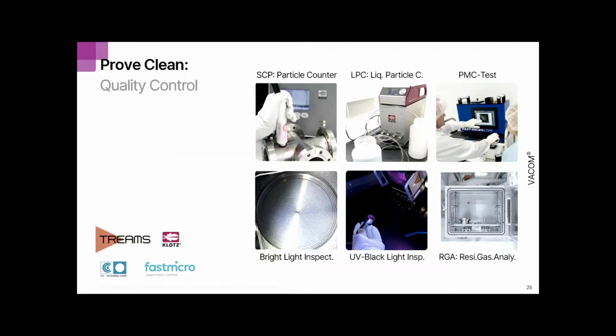So great, we've made the part clean, but you need to prove it as well. Otherwise, what are you doing? So for this, we have particle and filmic contamination specifications, for which we use different parameters and different test methods. So we have a particle counter, for example, a liquid particle counter, or a PMC test, which is a particle measurement card. For filmic contamination, you think about bright light, black light inspection, and RGA analysis. And RGA analysis is really a quantitative analysis which will actually give you information on the type of contamination that's left on your system. You can use it as a sort of troubleshooting if you're having issues with contamination of your assemblies, for example. You can use RGA to think about where that contamination comes from.